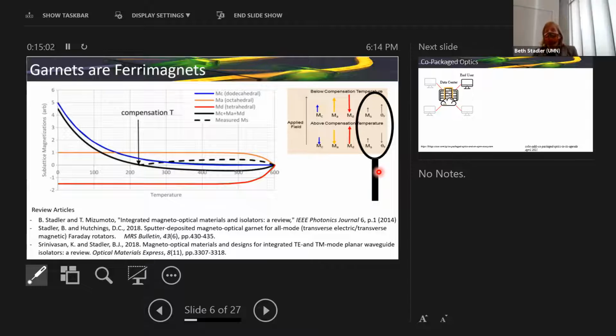So what a lot of people did, like in the 1990s, is they would take garnet grown on garnet, and they would heat up one area or cause a little diffusion to try to shift it. So they'd say, if I'm sitting at 300, and I make an iron gallium garnet, I can shift the compensation temperature from one side of 300 to the other, and every other segment of my garnet will be positive and negative and positive and negative. They did that just by barely shifting how much iron they had.